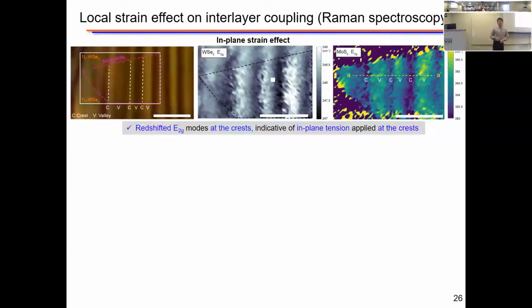We turn to Raman spectroscopy, which is a direct measurement of the strain effect. First we look at the E2G mode, which is sensitive to the in-plane vibrational mode. It says that there is tension at the crest and compression at the valley. So this is somewhat expected.